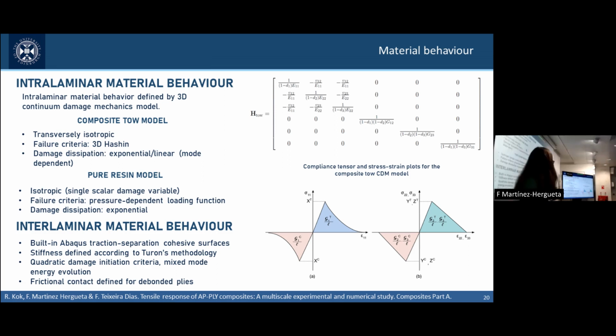Damage dissipation uses exponential and linear laws depending on the failure mode, and those are described over here. We've got some exponential laws for fiber failure and some triangular laws for matrix cracking. That means that this model already implements two of the main failure mechanisms we described before, matrix cracking and fiber failure. We are missing tow debonding. For tow debonding, we just implemented the cohesive surfaces that are already available in Abaqus, as this could have been done for a regular angle-ply laminate.